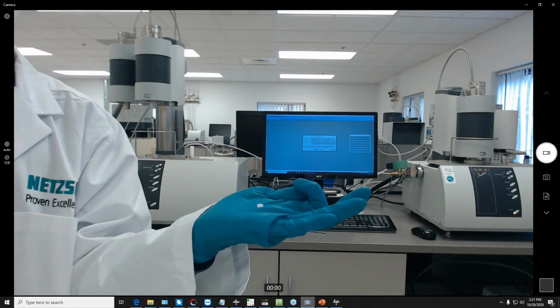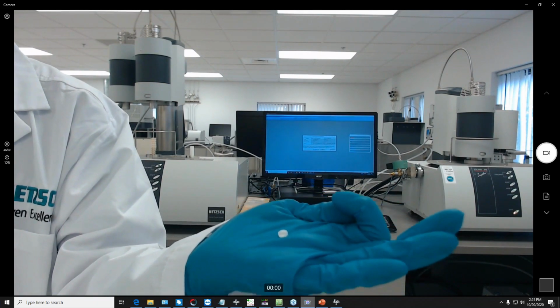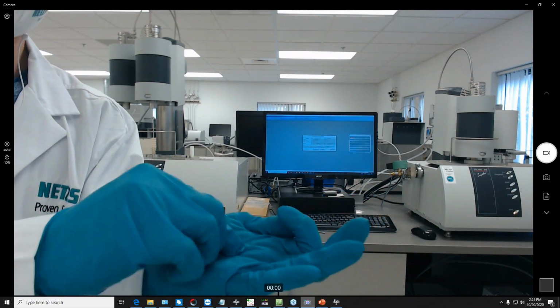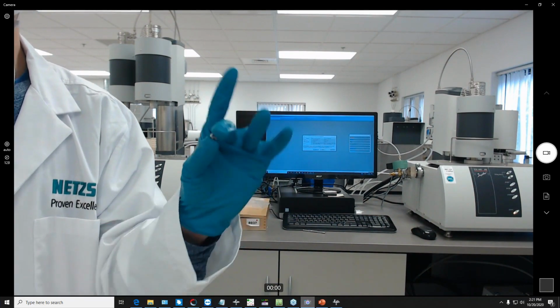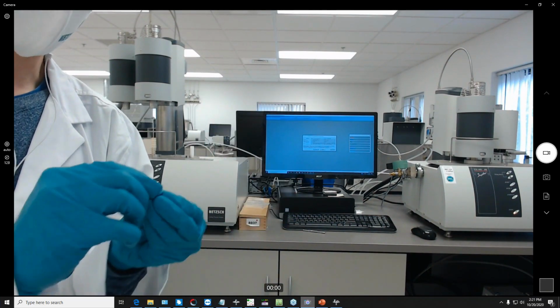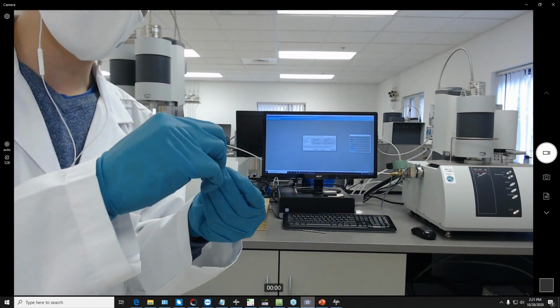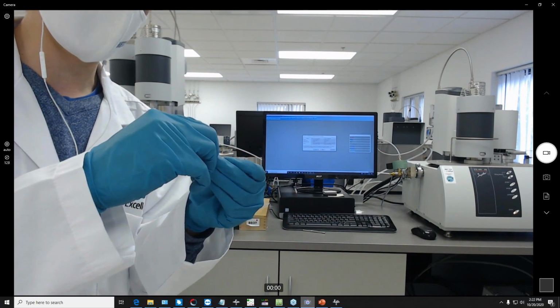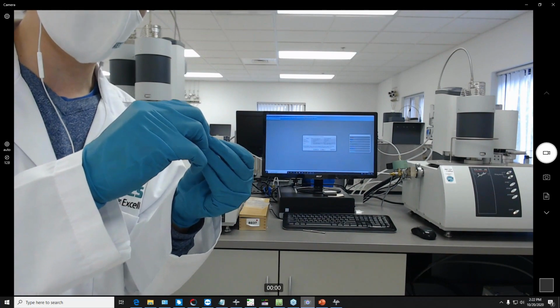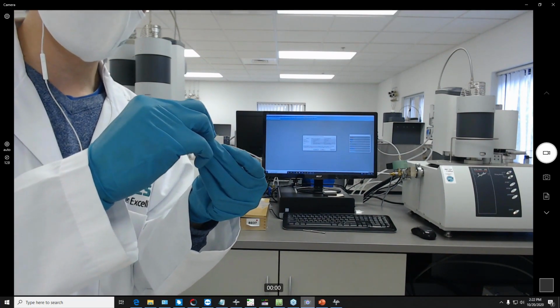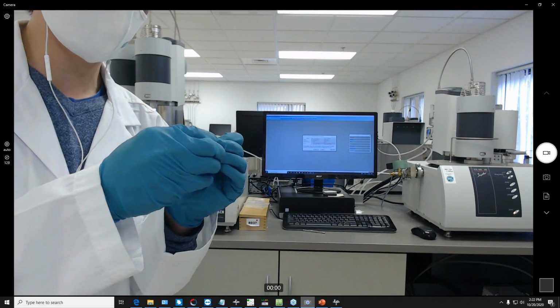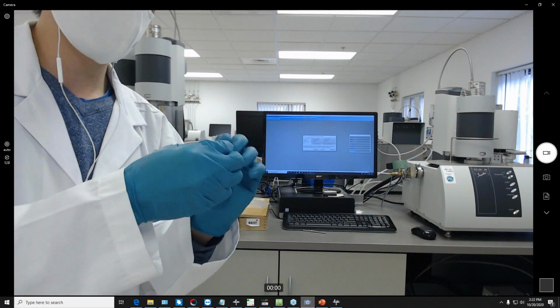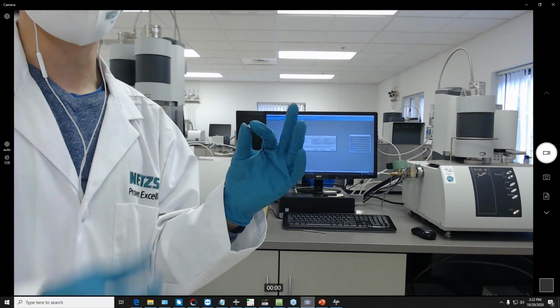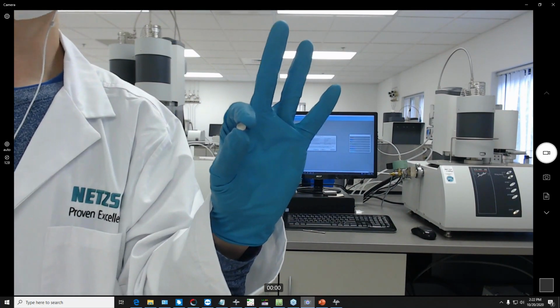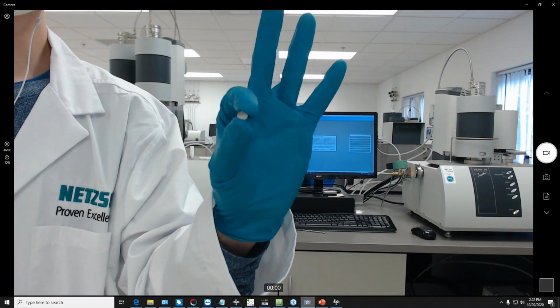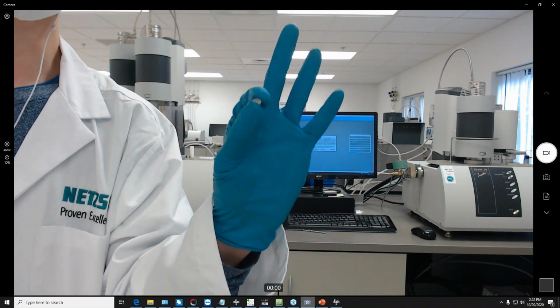The thin alumina liner is this white disc here. These can fit on the inside of a platinum crucible so that the contact with the sample is aluminum oxide, so it won't react with the platinum, but we still get the conductive heating properties of platinum so that you get good DSC signal and response. The aluminum oxide liner fits right inside, and then you can put a lid right on top.